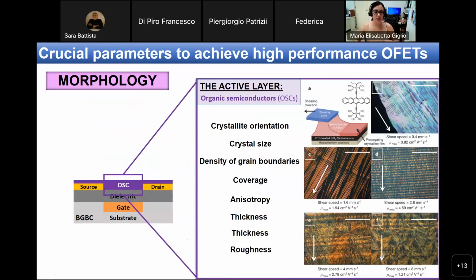So why is morphology so important? Morphology is so important because a lot of parameters, a lot of features of the morphology have a huge impact on the final performance of the transistor. So when we think about the film, we have to think about the crystallinity of the film, so the orientation of the crystals, the crystal size, the density of the grain boundaries, the coverage of the crystals, as well as the thickness and the roughness. And all these parameters can be tuned by optimizing the coating parameters that are mainly the speed, the temperature, but also the ink formulation.